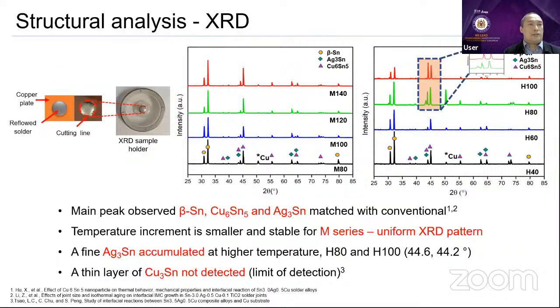Okay, this one is for the structural analysis. When we run the XRD, one of the problems is that the amount of solder here is very small, very limited. When we just cut and run for the XRD, the peak is normally dominated by the copper plate. So that is the reason you need to cut the rest of the area with just the sample and the copper behind it. So it tends to be very small here.